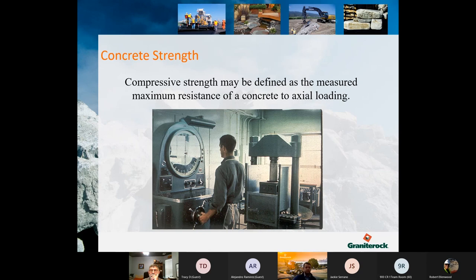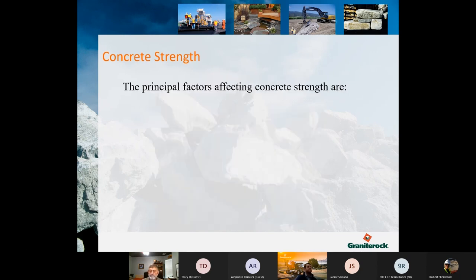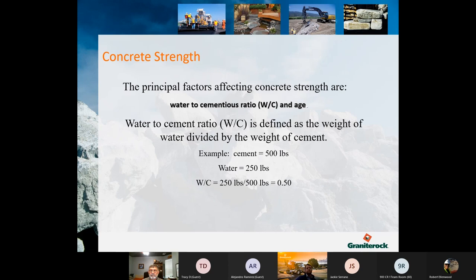Another property is concrete strength. Strength can be defined as the measured maximum resistance of concrete to axial loading. The principal factors are water cement ratio and age. Water cement ratio is defined as the weight of water divided by the weight of cement. Simple example here, 250 pounds of water per yard with 500 pounds of cement yields a 0.50 water cement ratio. And note that strength increases with age and also increases as the water cement ratio decreases. So it's something to watch for.